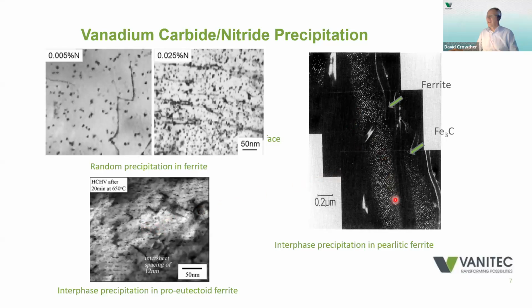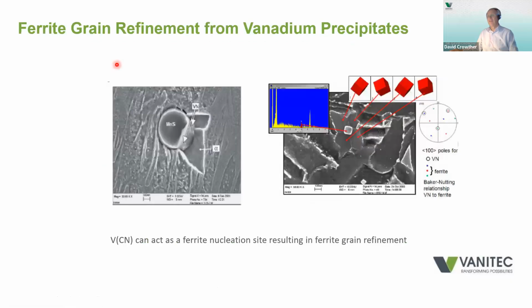On the right-hand side, and perhaps not so well known, is that you can get precipitation in pearlitic ferrite. So here we have the dark bands, which are the cementite in pearlite, and in between we have vanadium precipitates in ferrite. So the vanadium precipitates can harden the pearlite as well as the ferrite. Vanadium precipitates can also act as nucleation sites for ferrite, and hence refine the grain size.